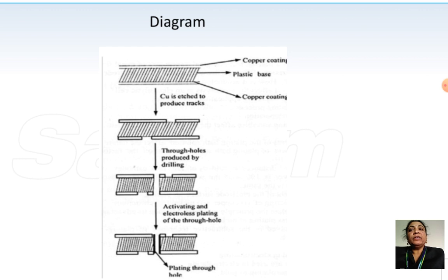The plating here is carried out at room temperature by dipping the activated plastic board in a bath solution. The temperature is maintained at about 25 degrees, as already said in the plating bath composition, and the process is continued until the required thickness is obtained.